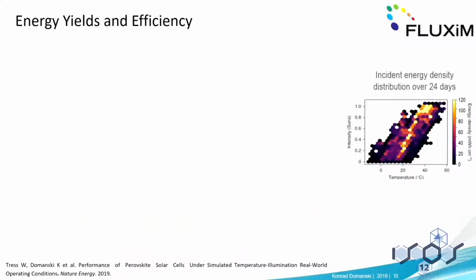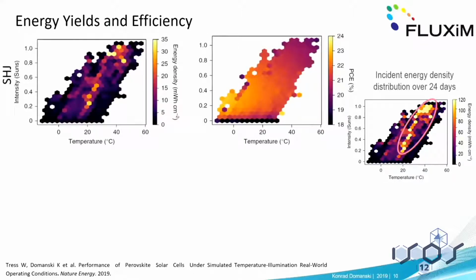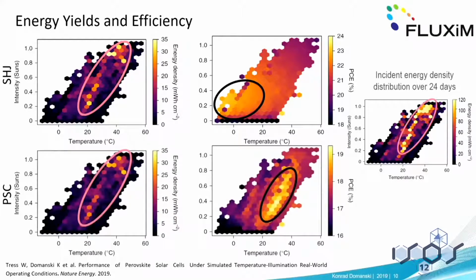So this is how the energy was distributed across our data. Here you see temperature and intensity, and we see that most energy is generated within this region. So now the question is how our cells respond to that region. For silicon, we see that most energy, again, is generated in this region. That's what we would expect. This is where most energy is shown on the device. However, the cells are most efficient in this region. So there is a slight mismatch. But okay. For perovskite, the story is a little bit more positive. Again, most energy is generated here, and the cells are also most efficient here. So that's a good match. That's what you would like.